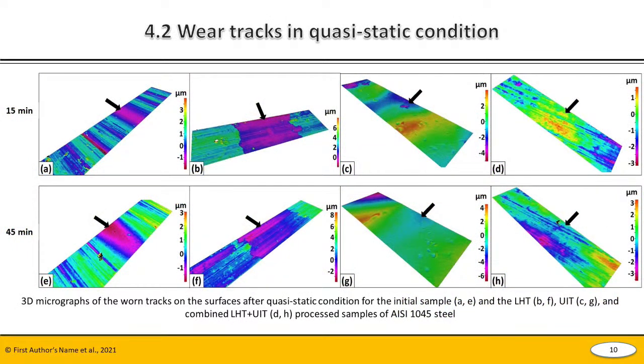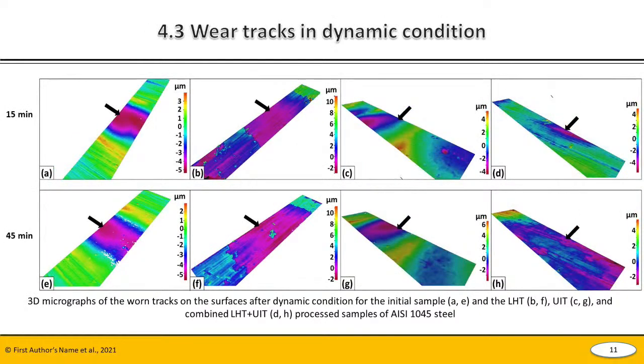The wear tracks in the quasi-static and dynamic conditions for the initial and treated specimens are presented on this slide in the second slide. This study was made using laser microscopy. It can be seen that the width and depth of the worn tracks, indicated by arrows, are larger after the dynamic wear test due to the application of additional alternating components of load. Next slide, please.